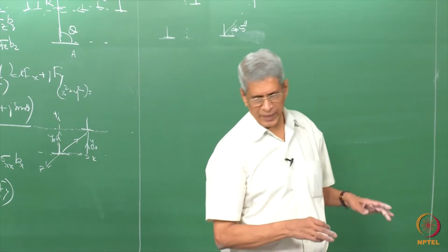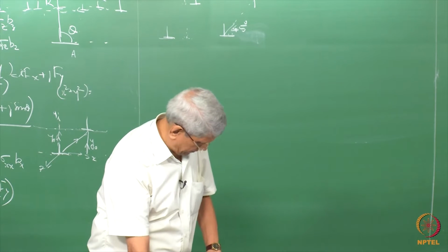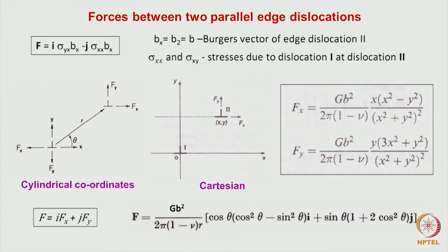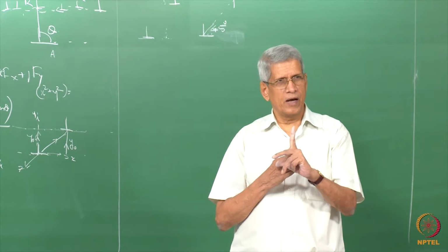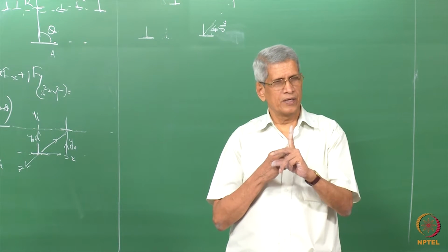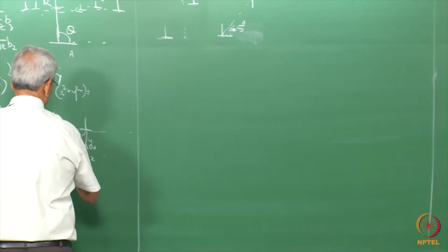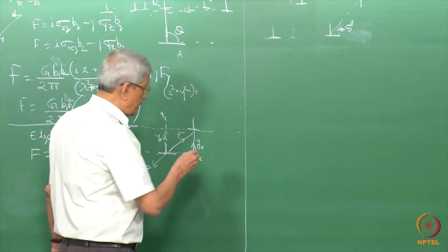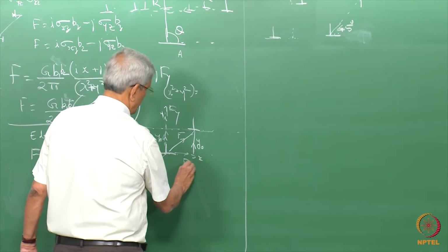Okay. This is how a dislocation dipole will form during deformation. This is considering room temperature. Now, let us consider the high temperature case. What will happen at a high temperature? At high temperature, we have to consider this force Fy which is going to act, because Fy is the force acting between the dislocations, that component. Because in any direction, the net force is going to be always between these dislocations in this direction. But we are splitting it up into a component Fy and a component Fx.